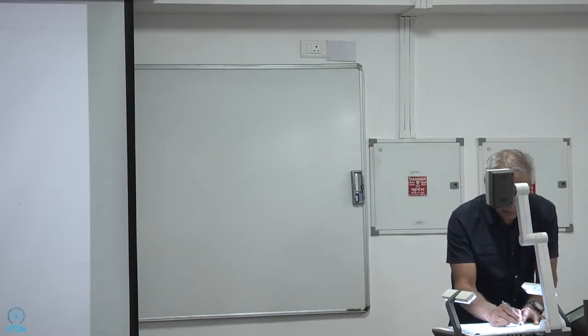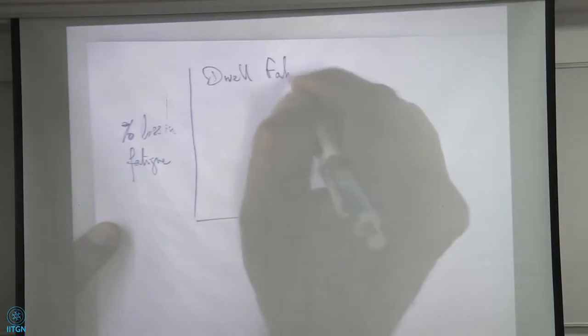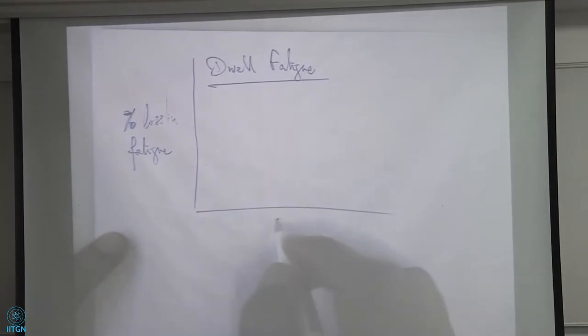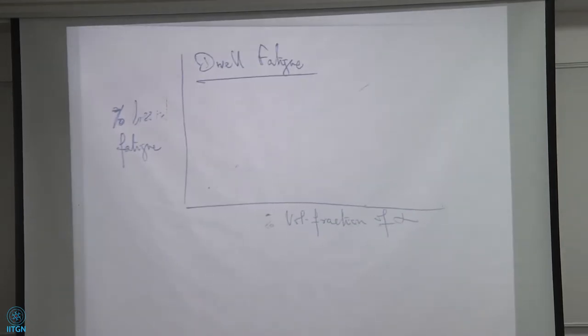So the experimental observations are titanium 6-4. I'm actually surprised that titanium 6-4, but near alpha alloys are the most affected. Anything like titanium 6 aluminum, titanium 6242, 811, these are near alpha, meaning there is more alpha content than beta, more aluminum stabilizers. They're very dwell fatigue sensitive, okay? But you will also see that these type of alloys also have a high degree of crystallographic texture. We'll talk about that in a little bit.